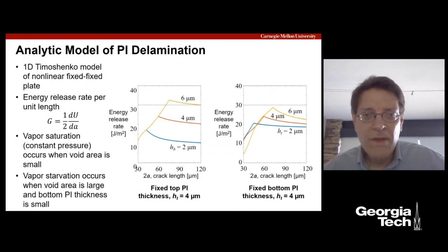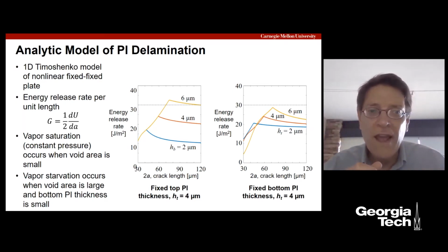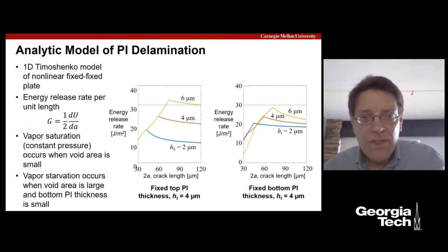Jacob Brenneman was the lead on this. He created an analytic model of this with energy release rate, which is the rate of change of strain energy in the system as a function of the crack area. A lot of times we think of energy release rate per unit length, in this case because we've got a line, so it's a derivative with respect to the crack length, which in our case is 2 times a.